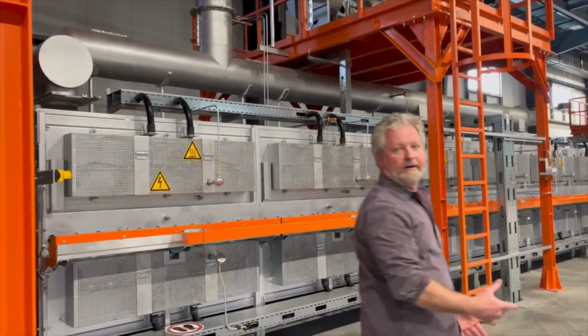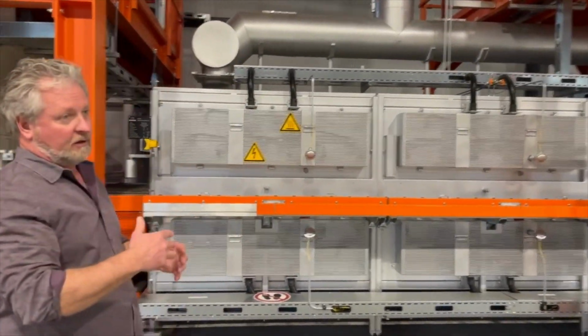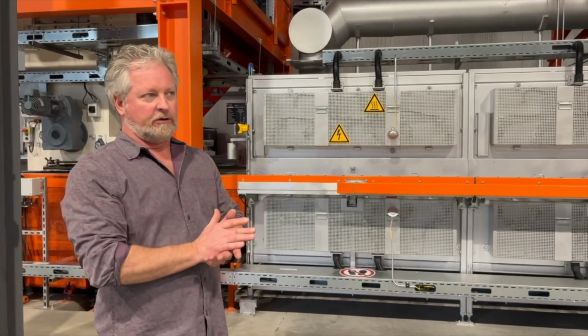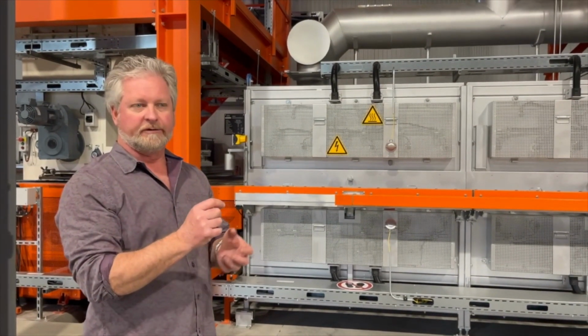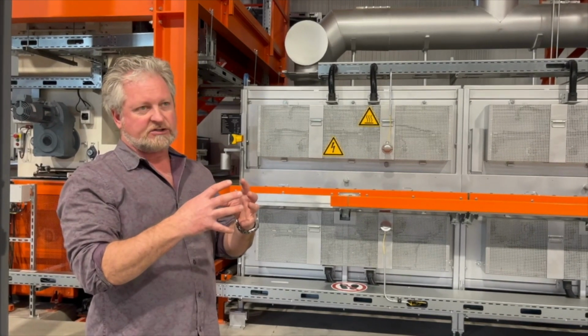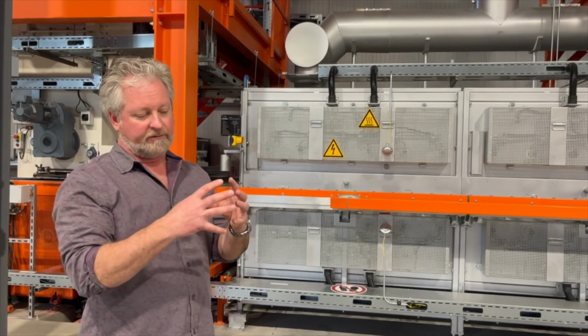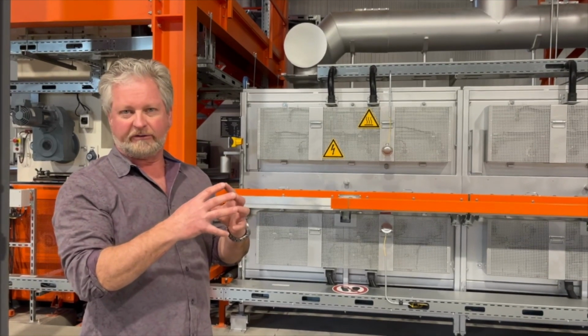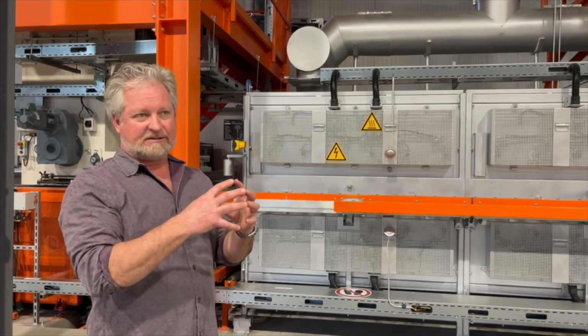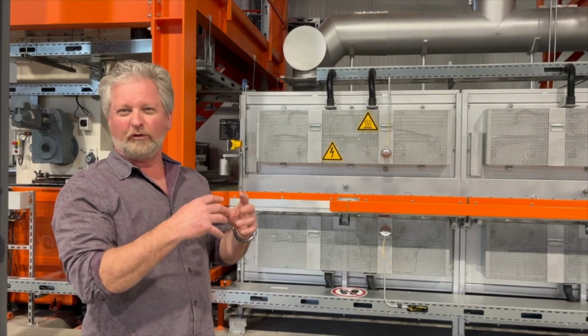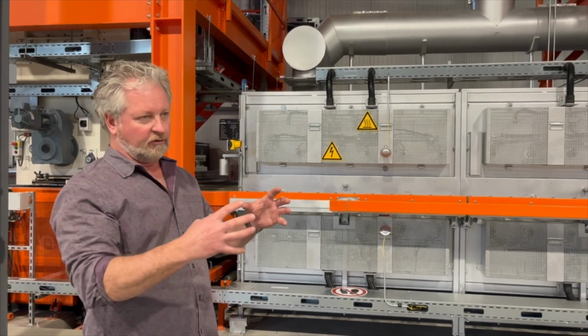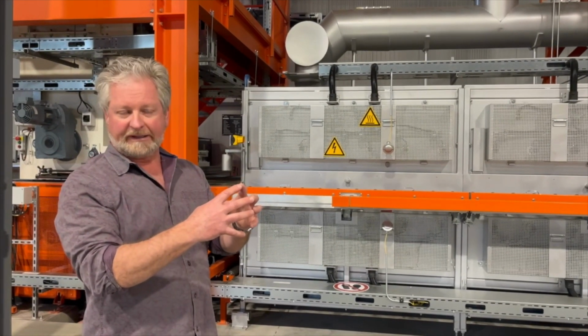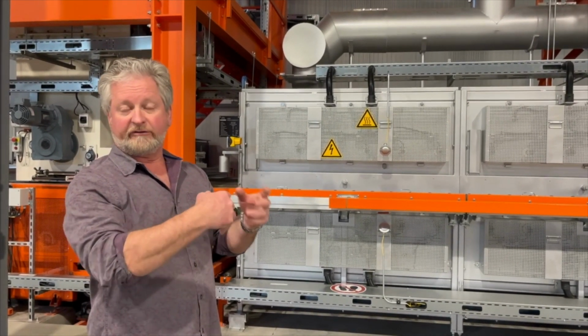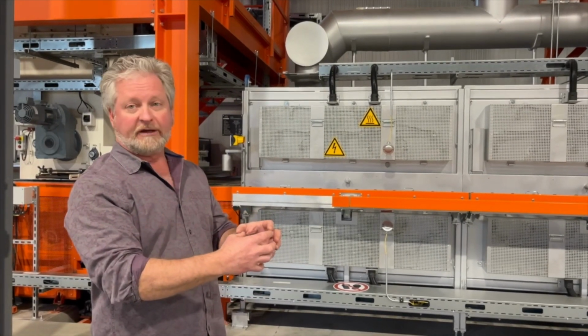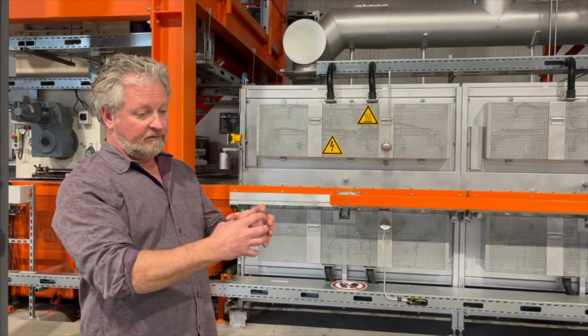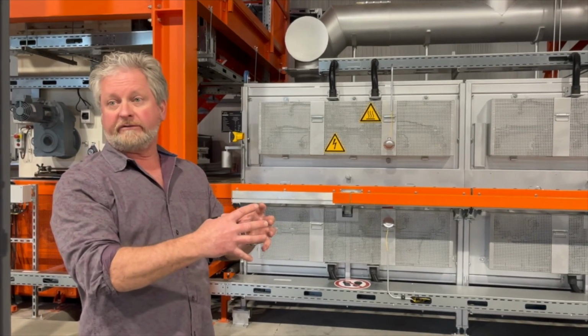The furnace is really the heart of the operation. This is a thermal process. What happens in the process is your glass powder, which is, as we mentioned before, very small particulates. As the heat starts to work the powder, the individual particles sinter, which means they start to physically adhere together. So the glass is starting to soften, but it's not fully molten. As the particles start to come together, voids exist between those particles, and the foaming agent generates gases that fill the voids between the particles and generates foam.